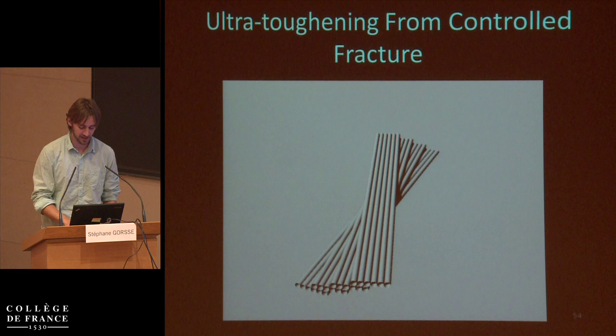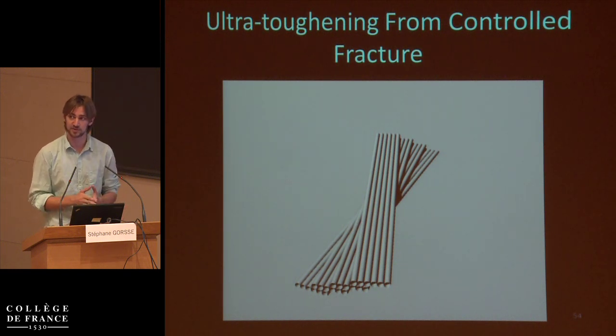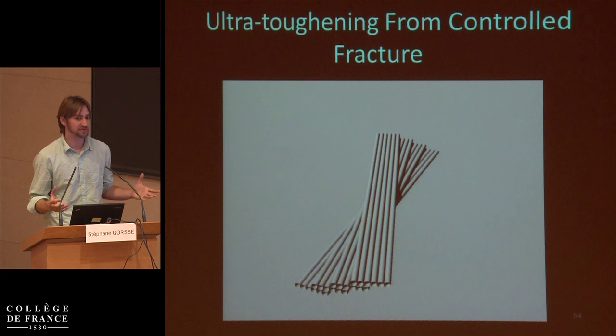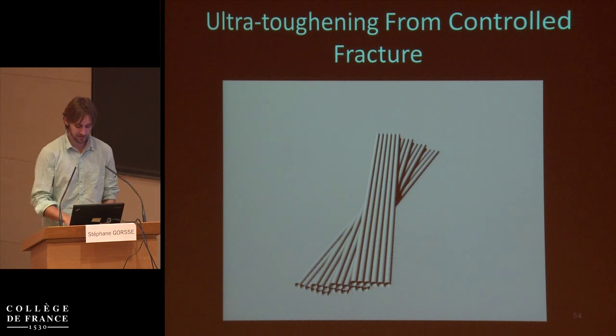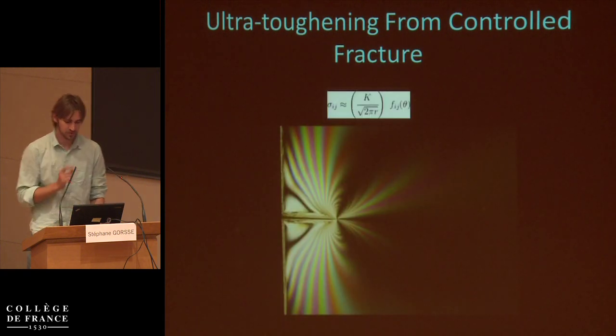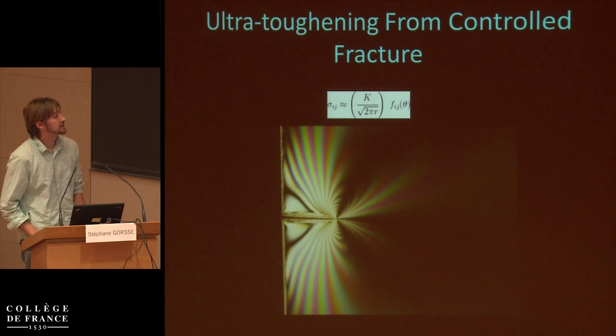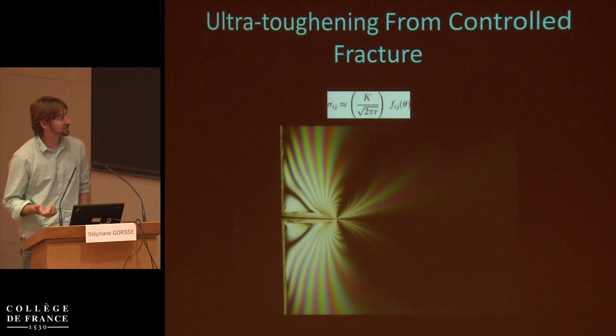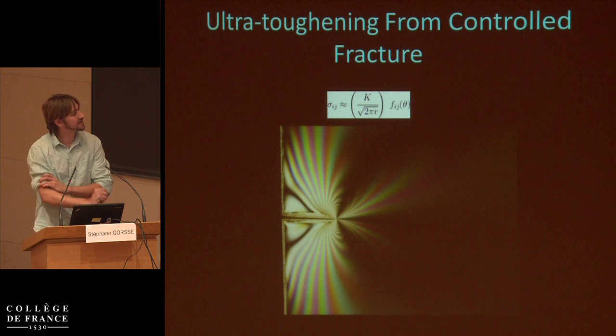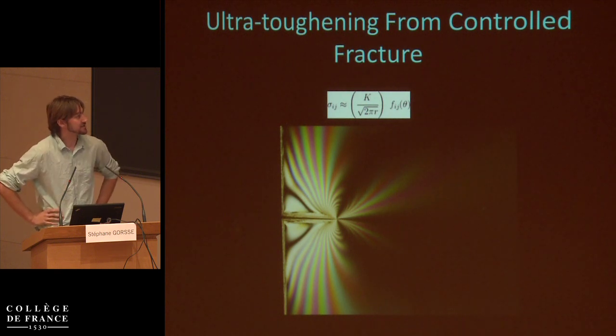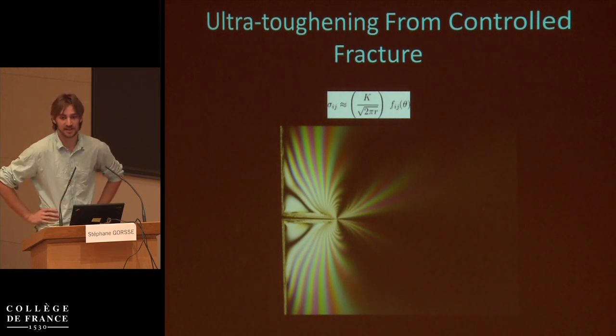And especially if you can keep any of those fractures from becoming catastrophic, then you can dissipate a vast amount of energy through the volume of your material, because all of the bonds within your material then become sacrificial, or potentially sacrificial. But there's one problem, and that's that unlike a lot of really interesting insights that we've learned from biomaterials, this one is not scalable. And that's because